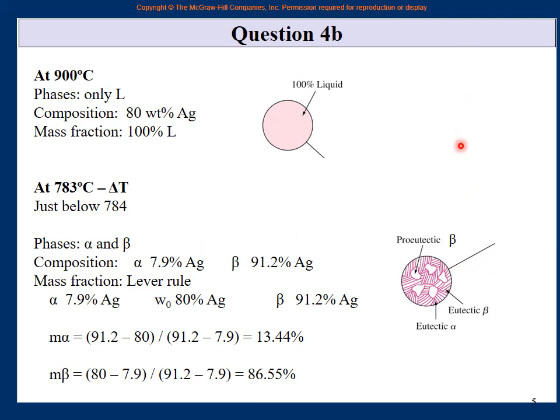So when you go from here and cut the liquidus, the first solids that form are beta solids, and beta plus liquid keeps on going until you get beta and alpha. So pro-eutectic beta is there, and then once you hit the eutectic line, all of that is converted into alpha plus beta, and that alpha and beta is eutectic alpha and eutectic beta. So these lumps are pro-eutectic beta, and all these dashed lines are eutectic alpha and eutectic beta together.